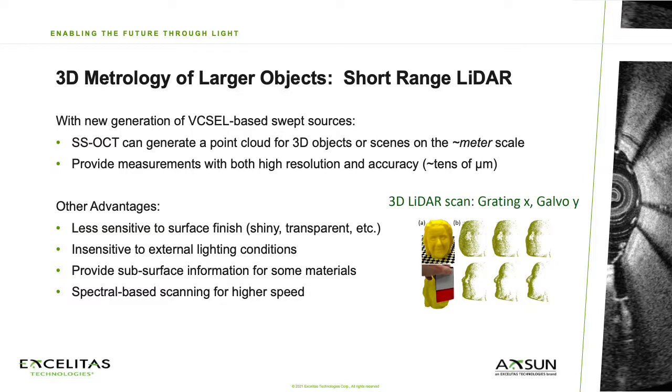Some advantages of swept source OCT technology include insensitivity to surface finish, which can be problematic for triangulation-based scanners, insensitivity to lighting conditions, which can be problematic for structured illumination and photographic scanners, and higher resolution and accuracy than time-of-flight laser scanners.